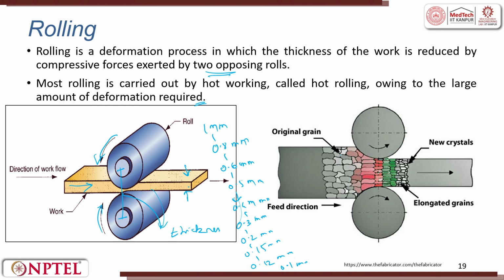So, this is the original grain which is there when you try to push it inside. The feeding direction is this. The rollers are moving in opposite directions, so that they bite and drag the material outside. Here, if you see the original grains, the grains are getting elongated, and then new grains get formed when it comes out of the roller zone. So, this is the deformation zone. When it comes out, you get elongated grains, and the new crystals are also getting formed.